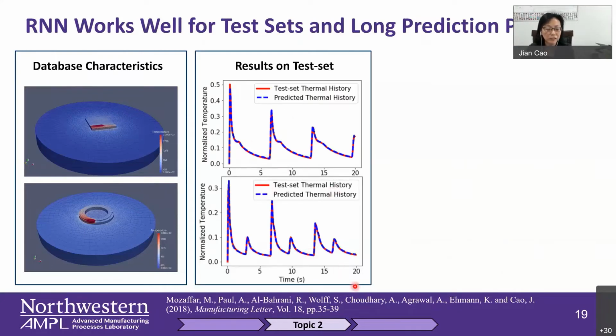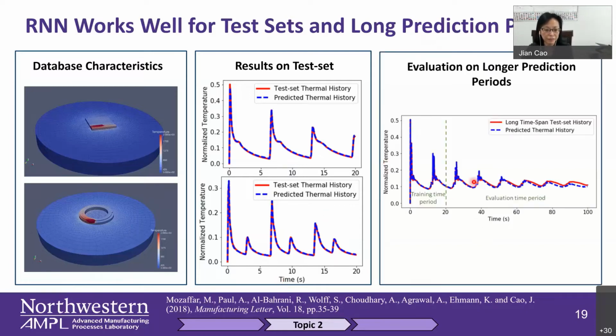Right. So the goal is, if we can predict this in a much faster way, then we can use it for control. And you can see that it predicts pretty well. It's not just predicting well at the beginning, because the initial 20 seconds we use for training, it's actually reasonably well even when you extrapolate a little bit. And as you know, for neural networks, extrapolation is always a danger.